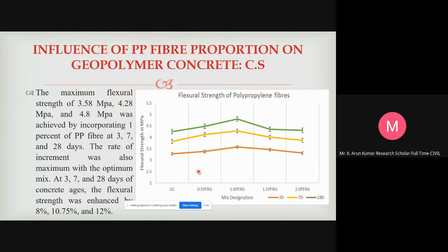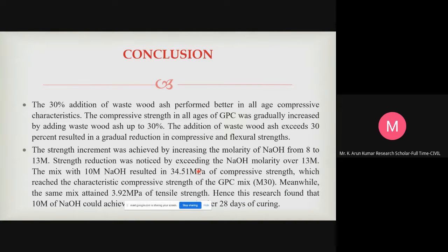Now, in the same way as compressive and tensile strength, the flexural strength was also optimum at 1% fiber addition. The flexural strength was 3.58 MPa at 3 days, 4.28 MPa at 7 days and 4.8 MPa at 28 days, where the strength increments were 8%, 10.75% and 12% on the respective days.